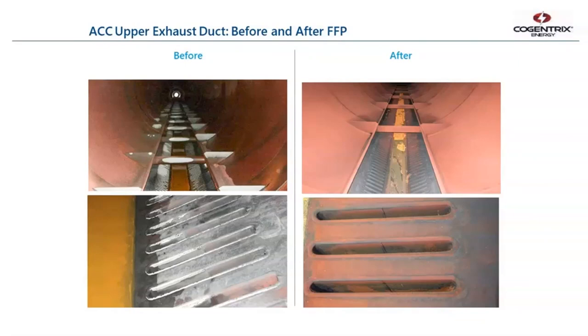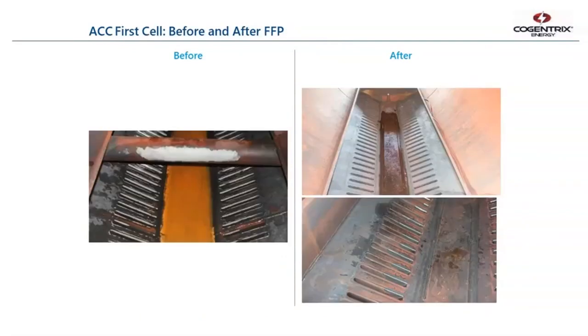You can see quite a big difference in the amount of two-phase FAC. The tube entries before were almost all completely wiped clean of passive oxide, and now it seems to be starting. And here's a close up of some more tube entries. This is on the near side where the steam first goes in. The previous picture was sort of towards the end.